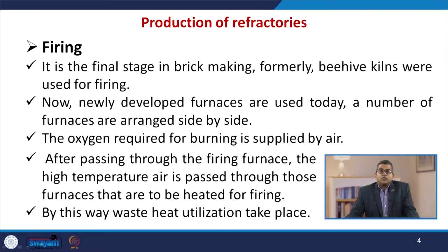Now, it is the final stage in brick making, and formerly beehive kilns were used for firing. Newly developed furnaces, those which are used today, are arranged side by side. Since during the firing oxygen is the key component, whatever oxygen is required for burning is usually supplied through air. After passing through the firing furnace, the high temperature air is passed through those furnaces that are to be heated for firing. In this way the waste heat utilization takes place.